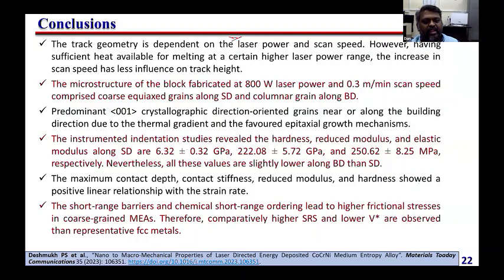That is mainly due to the thermal gradient, because layer by layer as we go, the heat will keep on accumulating. That will create some kind of thermal gradient. So that's why it leads to the epitaxial grain growth mechanism.